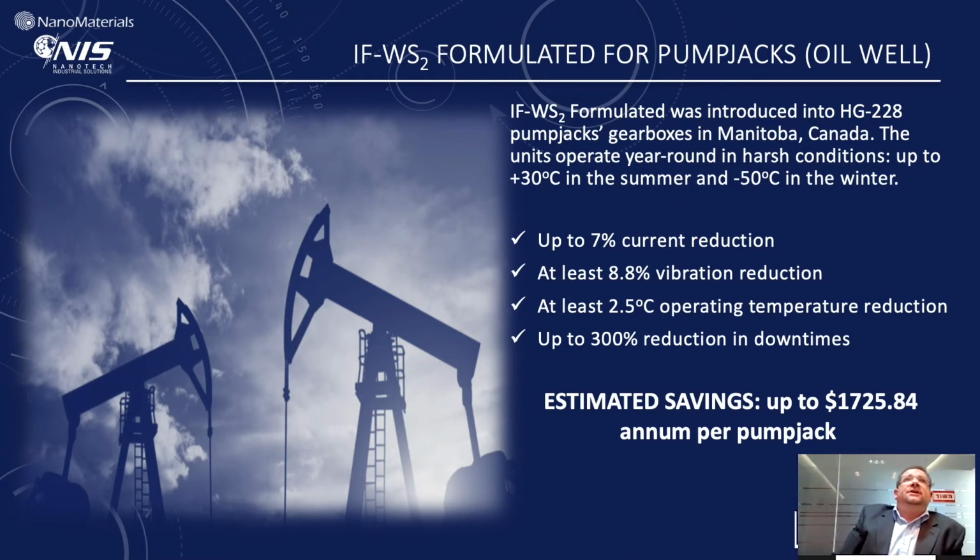One of the recent applications: our partners in Canada used the material in gearboxes of a pump jack and reported about 7% reduction of energy consumption in the operation of this pump, lower temperature of operation, and the most important, reduction in downtimes, which is very, very important for industry.